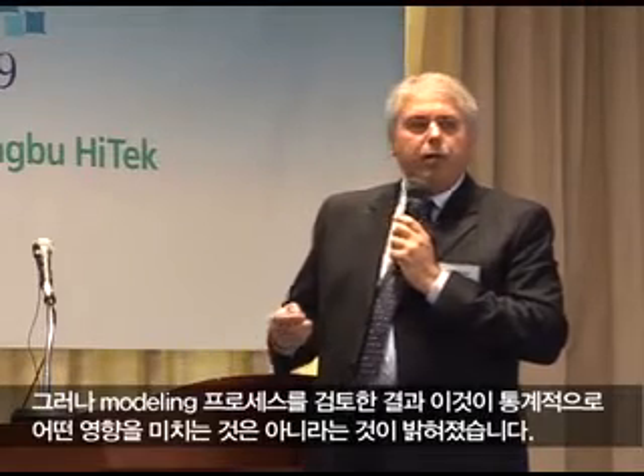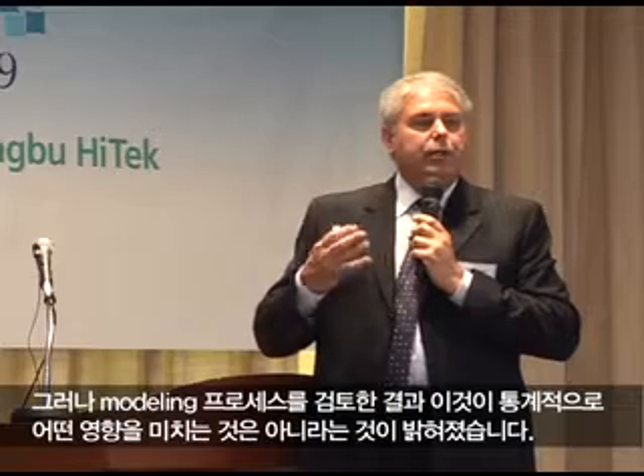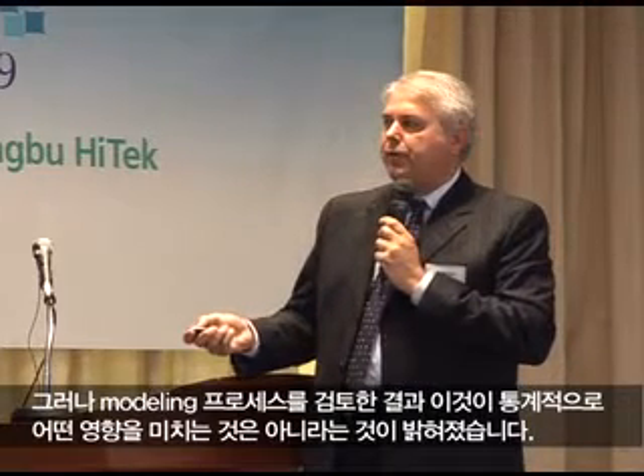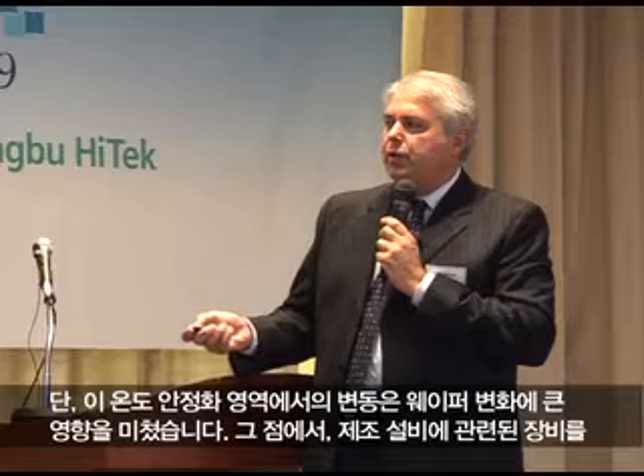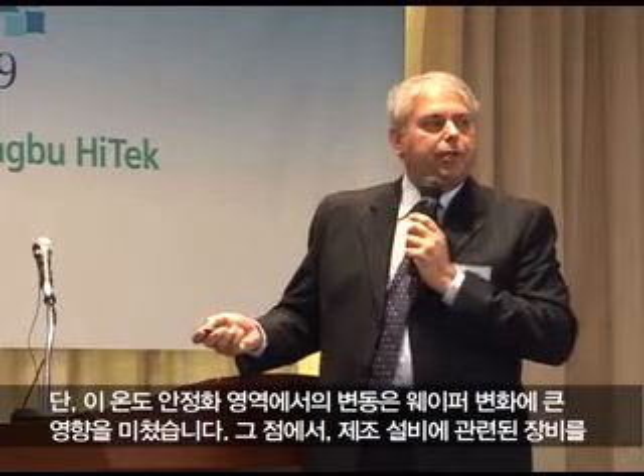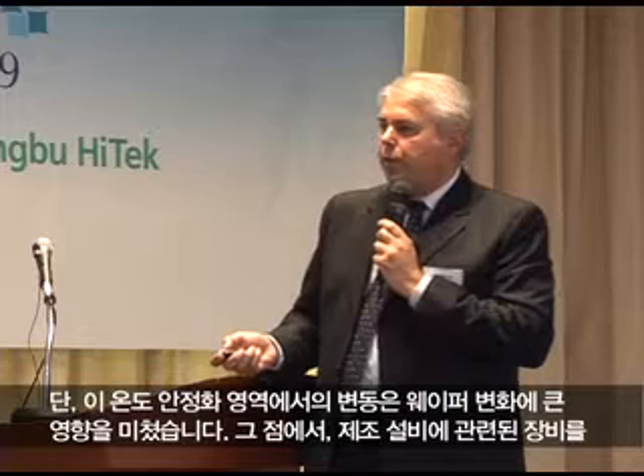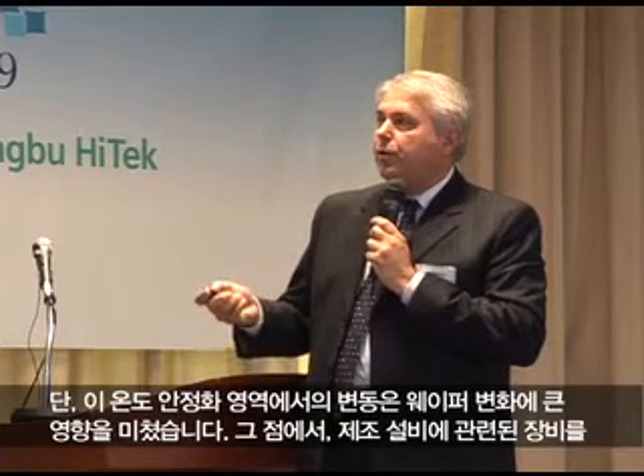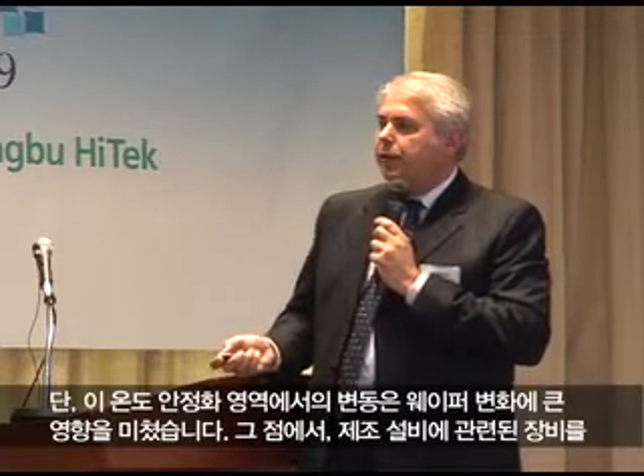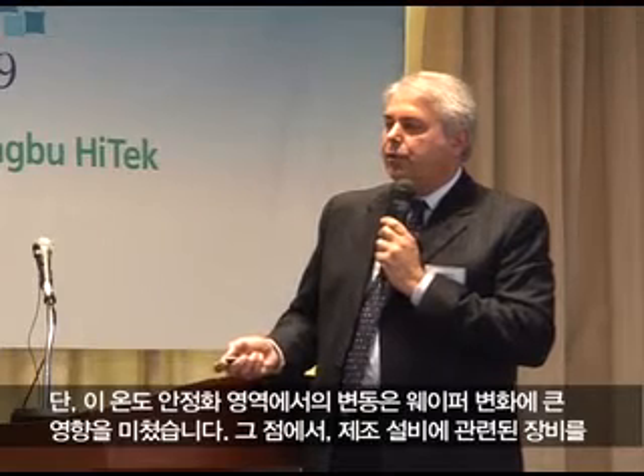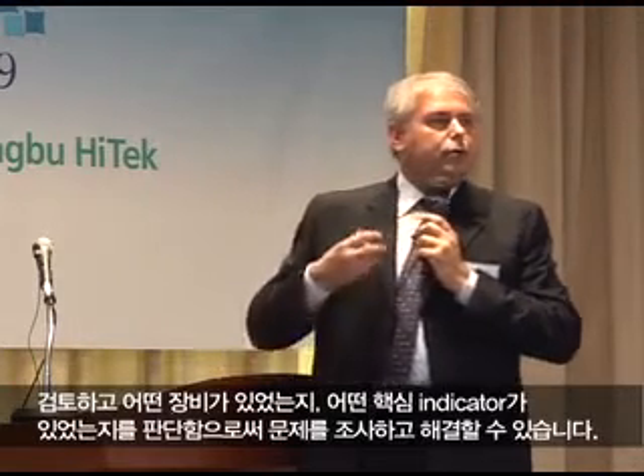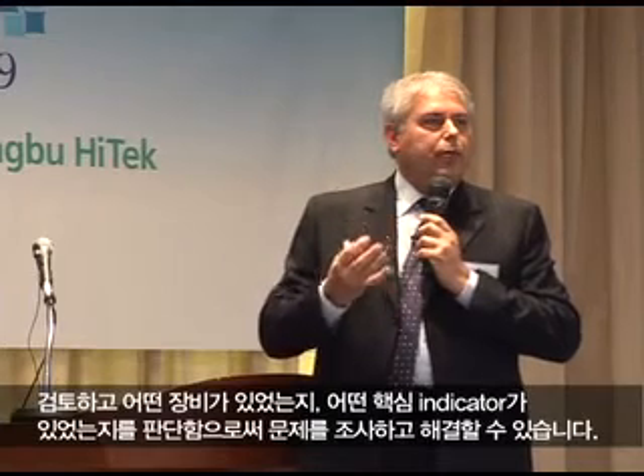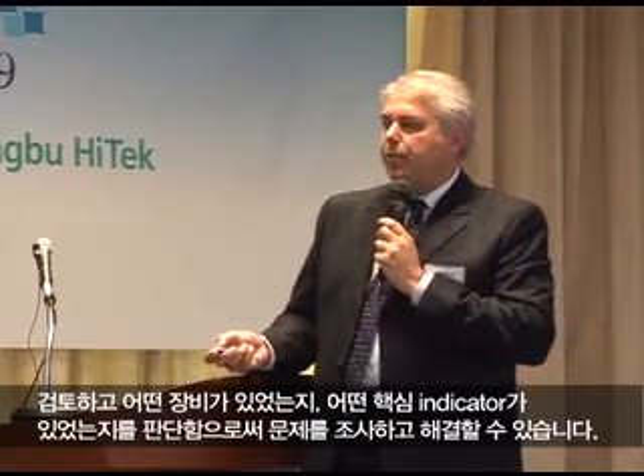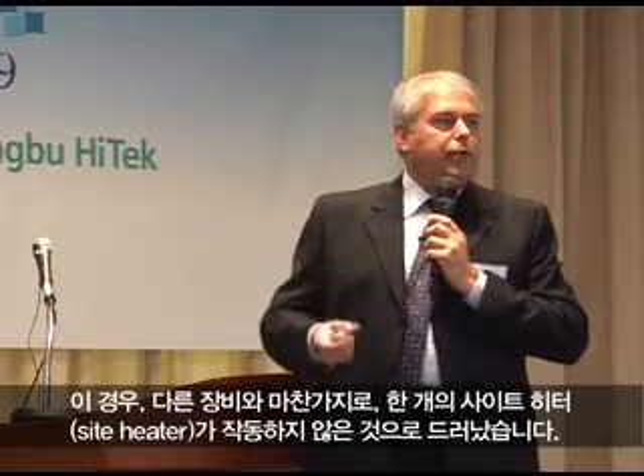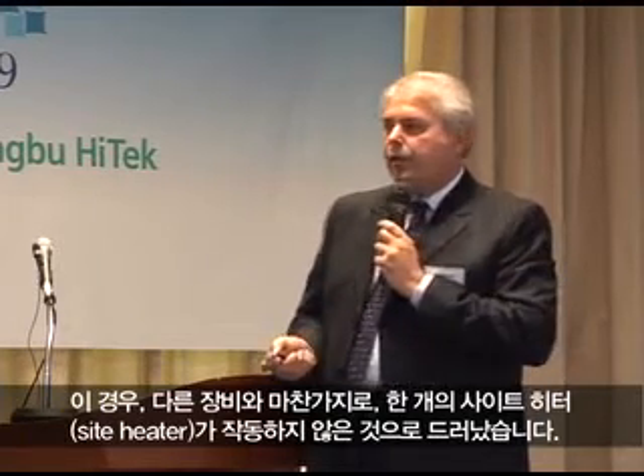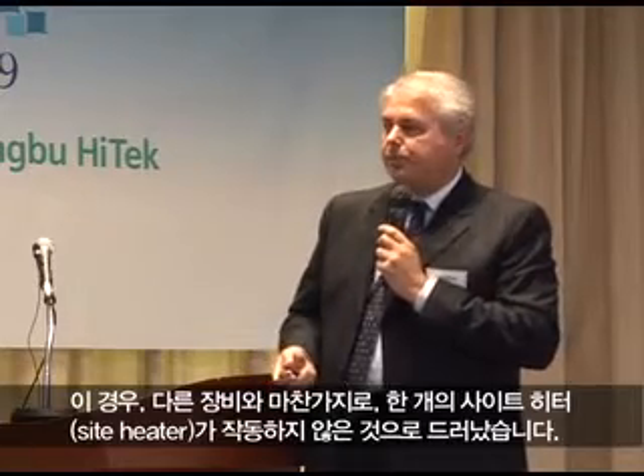But as we went through the modeling process, statistically this didn't show to have any effect, but variations in this temperature stabilization area had quite an impact on the wafer variation. And then out of that, actually the fabrication facility could go through the equipment. Now that he knows what equipment it was, what key indicator it was, he could go through and then correct the problem, which turned out to be one side heater was not operating like the others or like the other equipments.